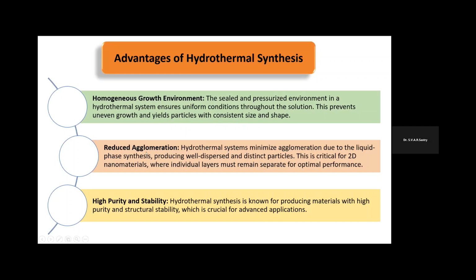We also have reduced agglomeration, because once the particles get agglomerated, we don't have nano size. It goes to 10 to the minus 7 or 10 to the minus 6 meters size, but we want nanoparticles. Agglomeration also has a problem: later on, when we mix this into lubricants as an additive, they will not mix uniformly, and it will also interfere with engine performance. So we don't want any agglomeration. This hydrothermal synthesis method minimizes agglomeration due to the liquid phase synthesis, producing well dispersed and distinct nanoparticles, which is critical for two-dimensional materials, where individual layers must remain separate for optimal performance in lubrication.